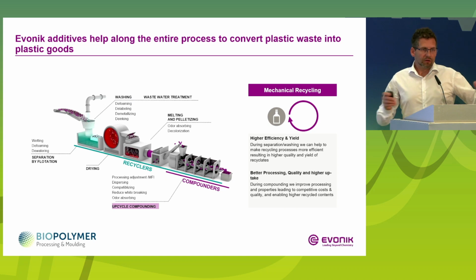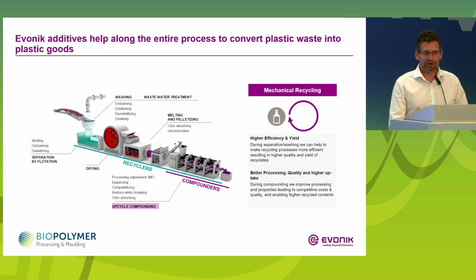Yeah, here you can see a typical processing of this mechanical recycling, starting in the beginning with a shredded and pre-sorted material, which is washed, and then we have this so-called sink-float bath, where we can separate by density, and then you have a drying step, a pelletizing step, and at the end a compounding step. And in these different steps, we have the possibility to improve this processing. For example, during the washing step, we have wetting agents for a better wetting, so that we improve the separation, so that no air bubbles stick on the heavy material, so that it floats up.